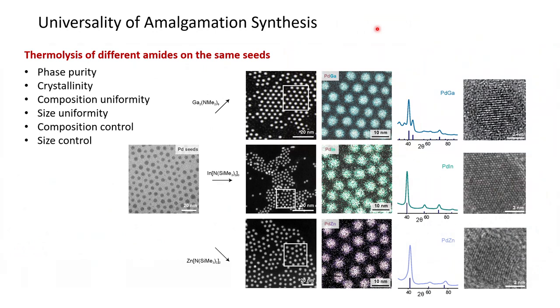Talking about the universality of our method, we can decompose different amides on the chosen seed, and the other way around, we can choose different seeds and decompose the amide on their surface. Let's take, for example, palladium seeds and decompose gallium, indium, and zinc salts on their surface, and this converts our palladium seeds to bimetallic palladium-gallium, palladium-indium, and palladium-zinc materials. You see from the X-rays that the materials are phase pure. Each nanoparticle has very good crystallinity. We can achieve composition control and size control, as well as composition and size uniformity.